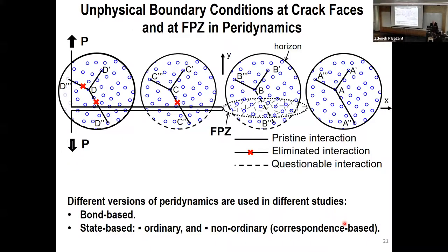The problem is not appreciated, that it is actually especially severe at cracks. The boundary was already discussed. So if you have a crack, then should point D interact with point D double prime? Of course not. So you have a boundary problem here, same as before. You have to cut it off. Far ahead of the crack, you have full interaction. But what about in the process zone, which in concrete is about 1 foot long?